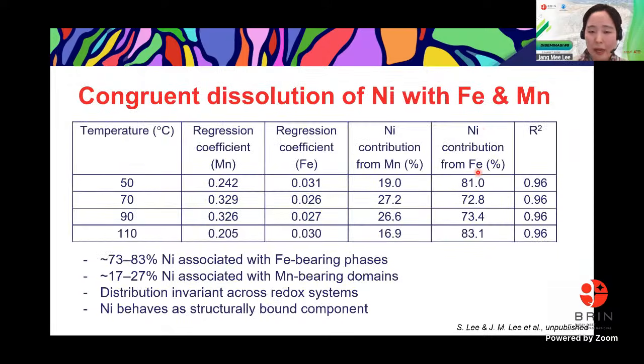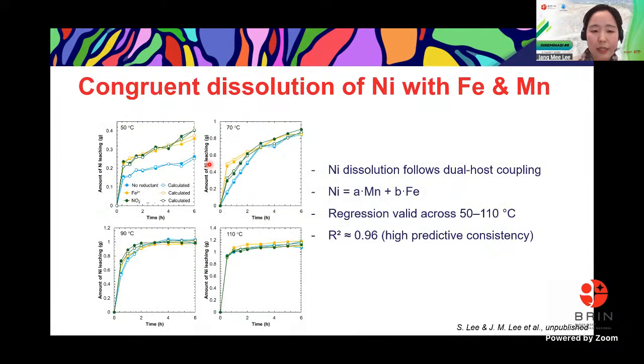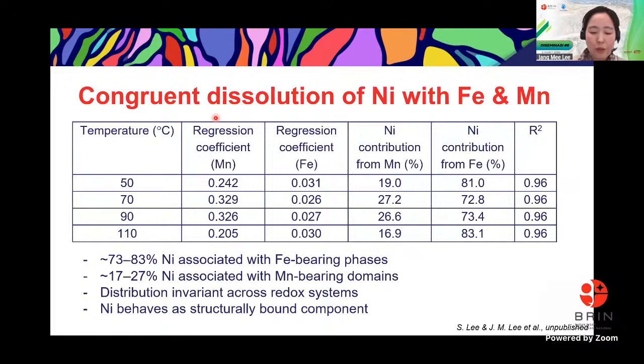And this is the table where we estimated the regression coefficient of each from the manganese phase and iron phase. And actually this is the amount of nickel leached in grams. This is not the leaching efficiency. So we did the mass normalization, and then we calculated the mass-normalized contribution. And as you can see here, 70 to 80% of nickel dissolution is associated with the iron phase, and around 20 to 27% of the nickel dissolution is associated with the manganese phase, we found.